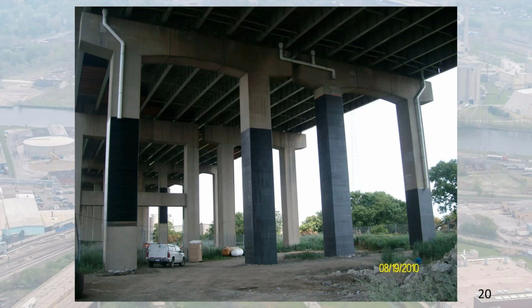The FRP subcontractor, since they were experienced, were able to use a particular device to ensure that the carbon fibers were fully saturated with the epoxy bonding material. They used an impregnating device that, similar to the old laundry squeegee rollers, you pass the fibers through a saturated roller system that makes sure the individual fibers are coated with the epoxy, and then they simply carefully place the wraps around the columns and then roll them into place to get rid of air bubbles.